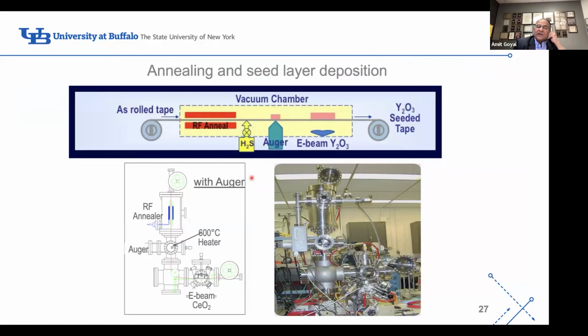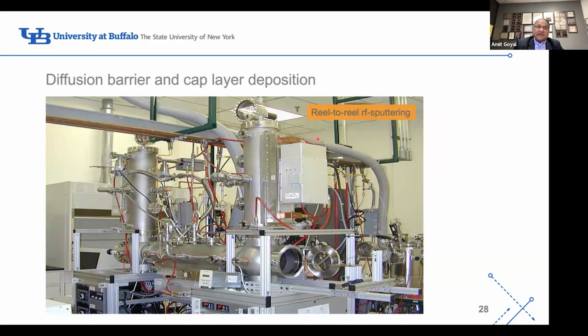We developed these reel-to-reel systems to demonstrate roll-to-roll deposition, which had never been done before. This is the schematic of the system. We leaked a little bit of H2S gas to automatically create the surface sulfur modification, a sulfur atom in every unit cell. We did online Auger to confirm we had the structure. Then we deposited the first buffer layer, the oxide layer. Then we designed additional systems. There's linear sputtering systems that we developed at Oak Ridge to demonstrate that this all can be done.